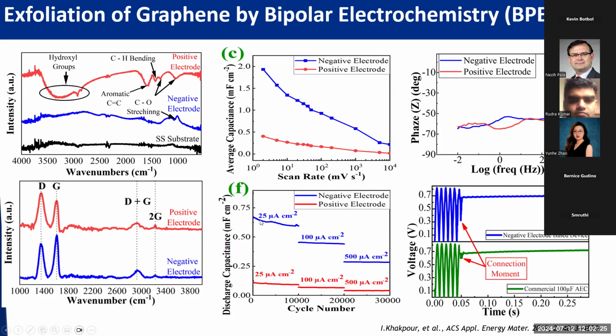As a supercapacitor, we found the performance is much, much higher than the graphene oxide deposited on the positive feeding electrode. So the reduced graphene oxide with its unique morphology can give much better performance. And the application for this is that we even try to use a negative feeding electrode based capacitor to replace a commercial aluminum electrolytic capacitor, which is very big. We made a small microcapacitor, and we can replace a bulky commercial electrolytic capacitor to achieve the same filtering effect.